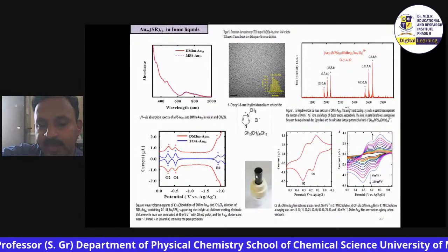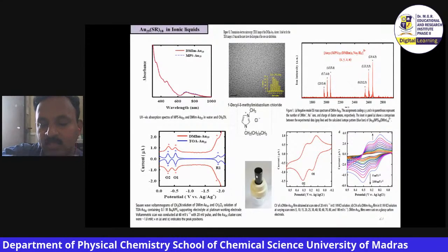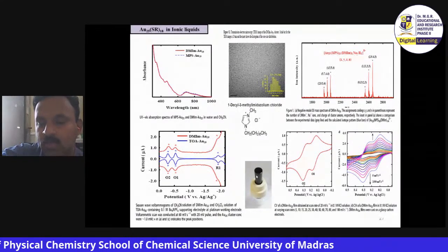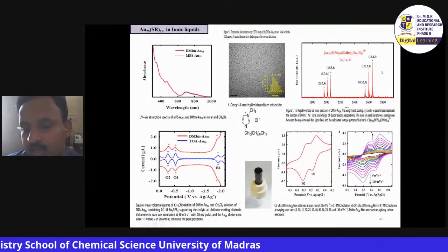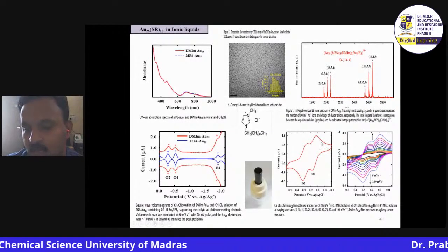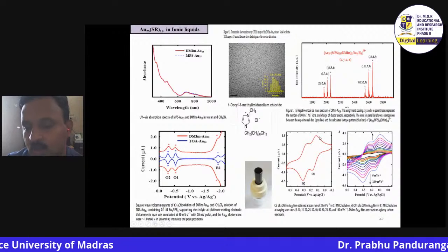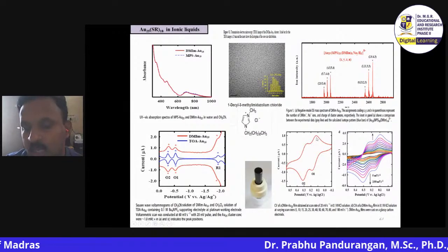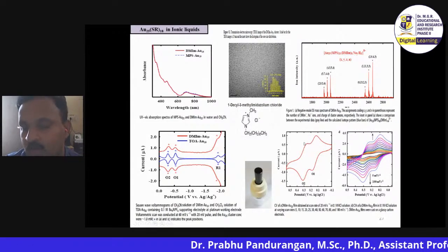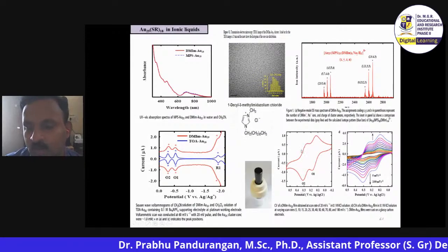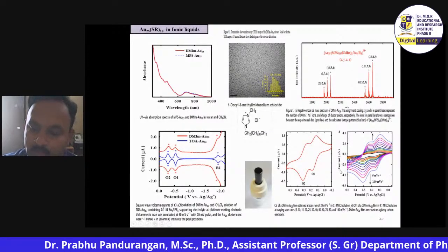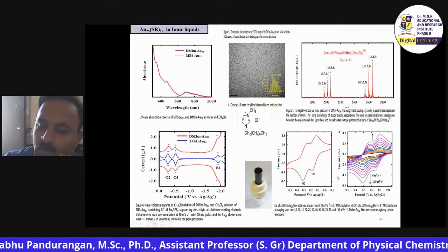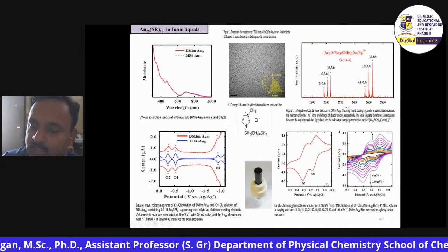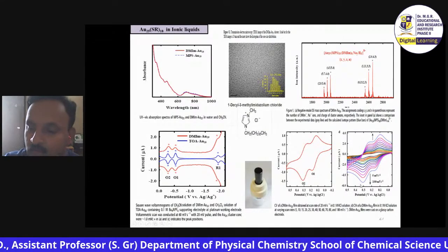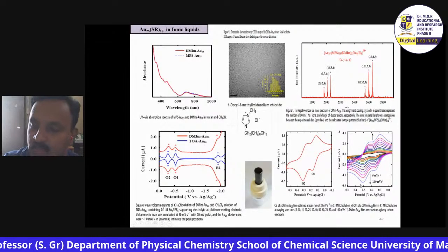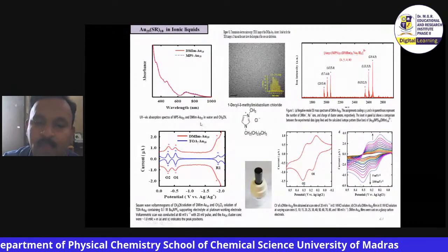So we need an ionic liquid matrix to make this particle stick onto the electrode, and thereby you are getting this response. You can see the first oxidation peak is because of the -1 to 0 state and 0 to +1 state with the second oxidation, and you can see beautiful redox behavior from gold. This is a historical paper on developing a sensor based on gold redox activity. Based on scan rate, this response also differs.